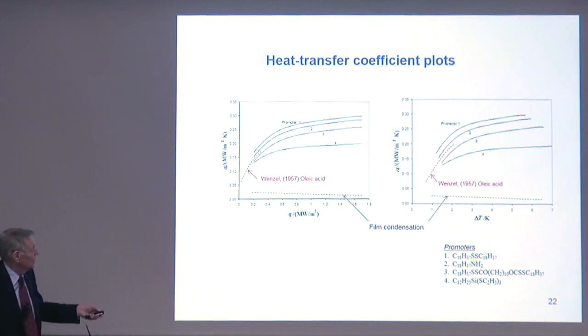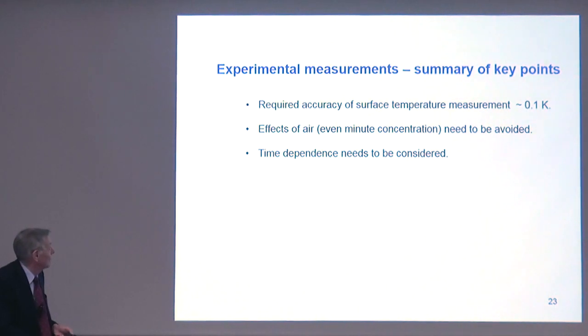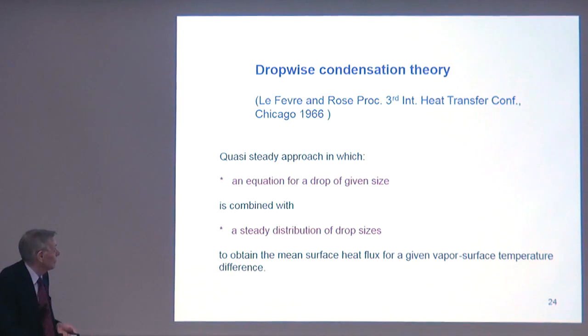These promoters are these. Wenzel used oleic acid. Clearly fits into the pattern. Summary: required accuracy should be at least this. The effects of air, even minute concentration, need to be avoided, and the time dependence needs to be considered.